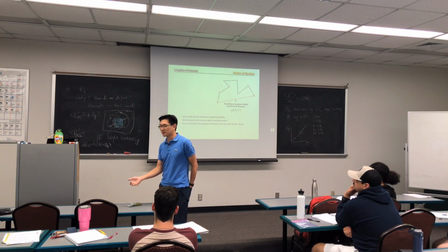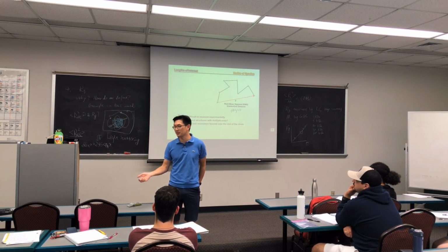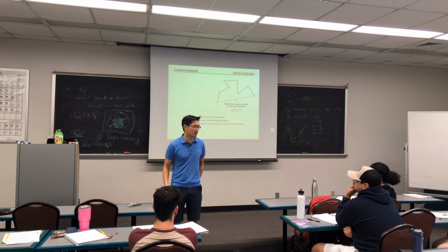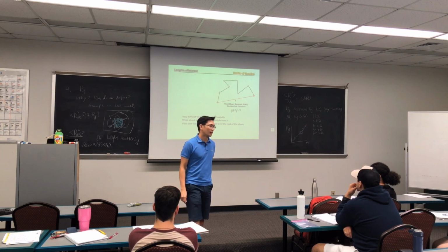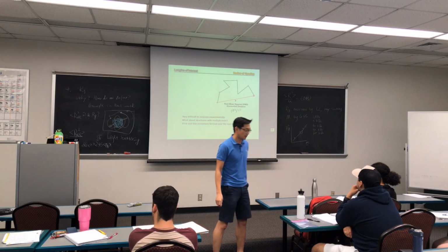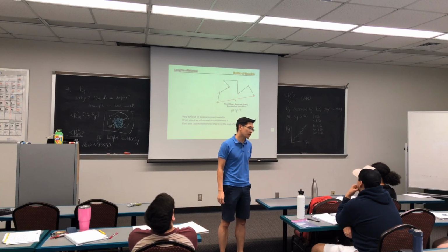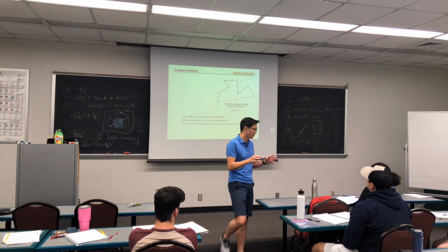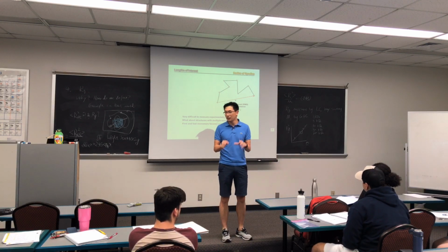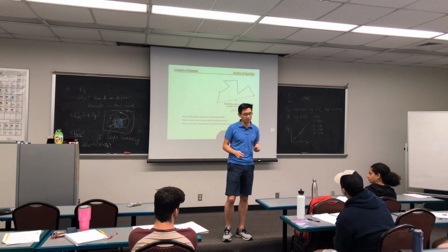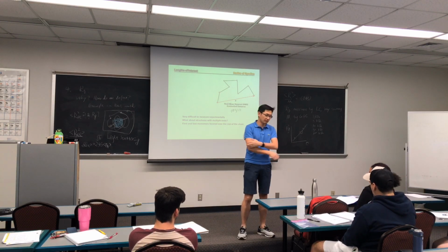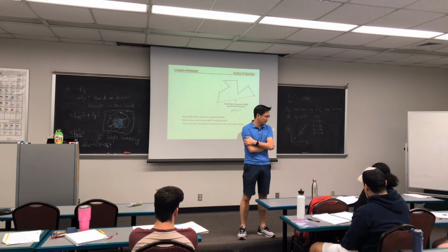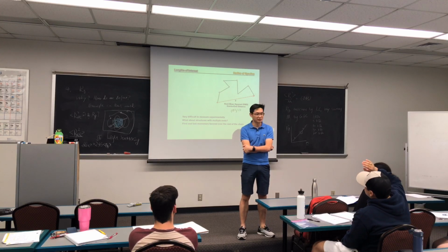They ask you to compare your material with polystyrene, and you need to do a similar experiment to understand the dependence for your polymer. Of course, there's something more to that calculation because chain conformation is dependent on solvent quality, but you can generally get a similar plot and quantify C infinity, as well as persistence length.